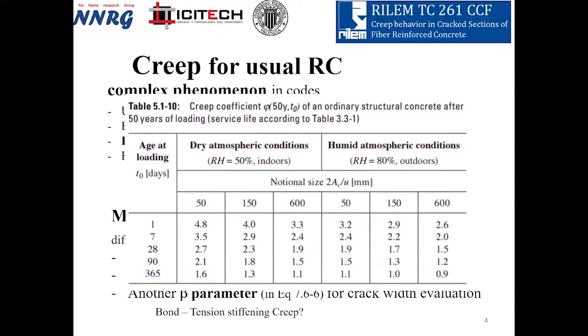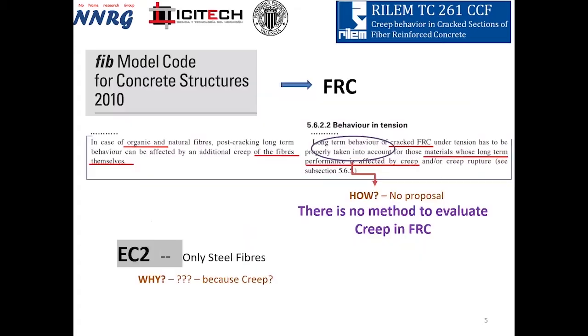Well, finally, we usually have a table like this where we apply different coefficients that can change a lot. And then we do not have a logically defined criteria even for standard concrete. When we introduce fiber reinforced concrete in the model code, one of the first aspects that appears is a warning that if you use synthetic fibers, you must consider the possibility of a creep effect of the fibers by themselves. And if you do that, you must take into account this effect. But there is never a criteria to evaluate that.